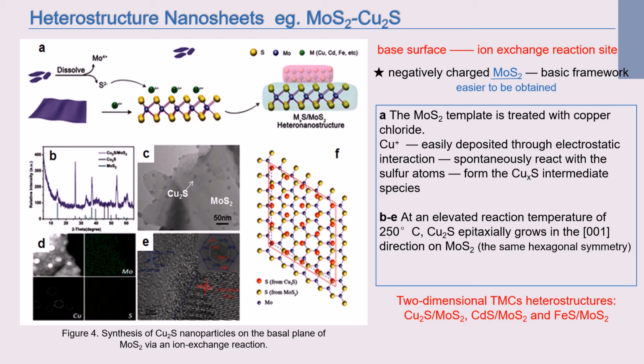And in Figure B to E, at an elevated reaction temperature of 250 Celsius, cuprous sulfide epitaxially grows in the 001 direction on molybdenum disulfide because the two samples have the same hexagonal symmetry. The epitaxial growth on molybdenum disulfide nanosheets is a general way to prepare two-dimensional heterostructures, such as cuprous sulfide on molybdenum disulfide, cadmium sulfide on molybdenum disulfide, and ferrous sulfide on molybdenum disulfide.